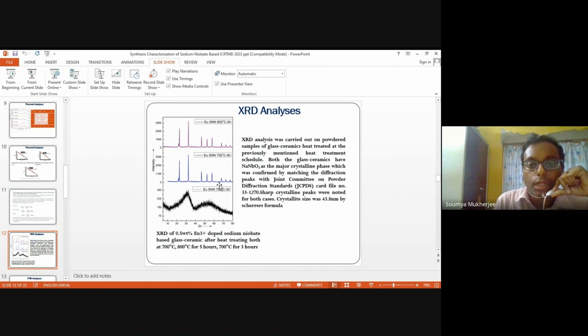With changes to higher duration periods, say 5 hours, we are getting a proper crystalline phase, and obviously at higher temperature, a crystalline phase with no other impurities. It is a sodium niobate based system. Obviously, with the change in temperature, what happens is the diffusion process gets assisted and the crystalline order is getting restored. That is the main change, and it has been verified from the JCPDS data card. And we have only calculated the crystal size for 700°C because we want the lowest temperature for crystallization, and we are getting the crystallite size to be 43.8 nanometers, which is close to 44 nanometers.